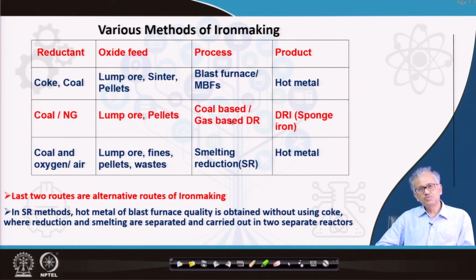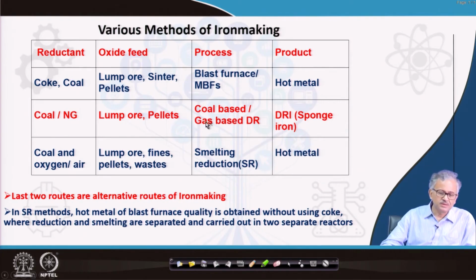But you can also reduce the iron ore by reformed natural gas. You take the natural gas, reform it to CO and H2, and then put that gas into the shaft furnace to reduce the ore. That is called the gas based DR process, and this is the coal based one. And what are the reductants here? Coal, non-coking coal, for the coal based DR process, and natural gas for the gas based DR process. And here the oxide feed is lumpy ore or pellets.